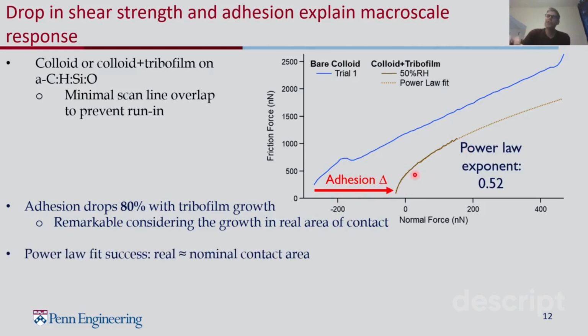Additionally, we can see that the shape of the curve changes a lot. So instead of being linear, it obeys a power law. And the exponent of this power law is about 0.52. And if this were a true Hertzian contact, you would expect a power law exponent of 0.66. In fact, it's a little bit lower than that. And we attribute that to the fact that the surface of the tribofilm is relatively flat, not hemispherical. So it behaves a little bit like a punch probe, where you would expect the power law exponent to be 0 instead of 0.66. So the fact that it's intermediate between these two makes sense.